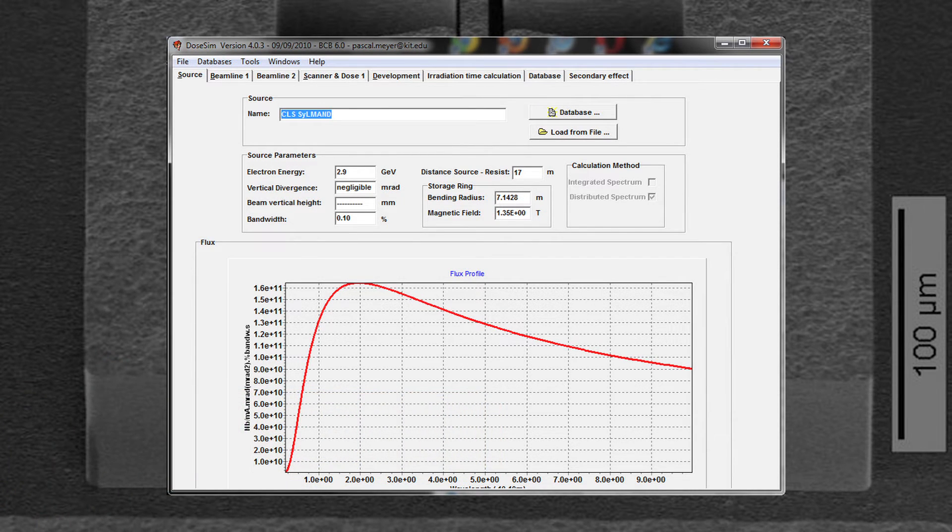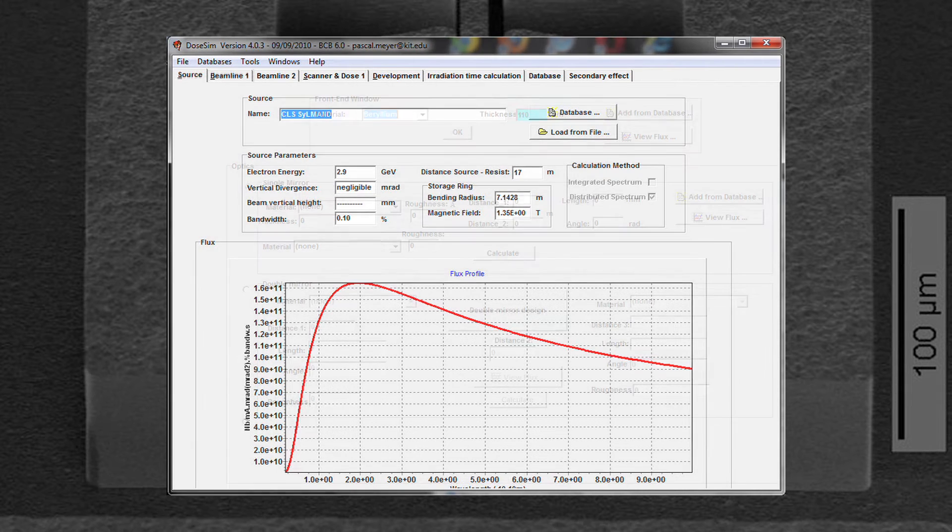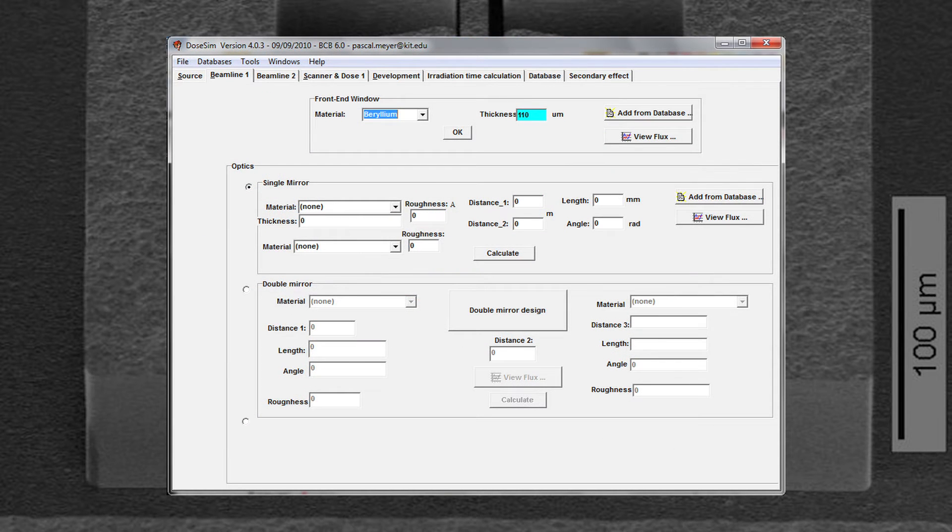Depending on the type of mask, resist thickness, and the feature sizes of the microstructures, a dose calculation is done using custom-developed software called DoseSim. During the process of dose calculation, appropriate settings for the mirror system grazing angle and the chopper settings are used to reduce both the intensity of the incident X-ray beam and to tune the spectrum.